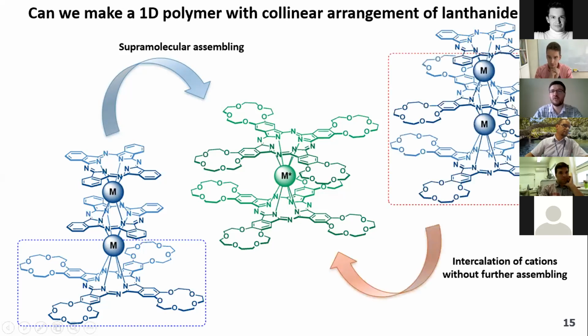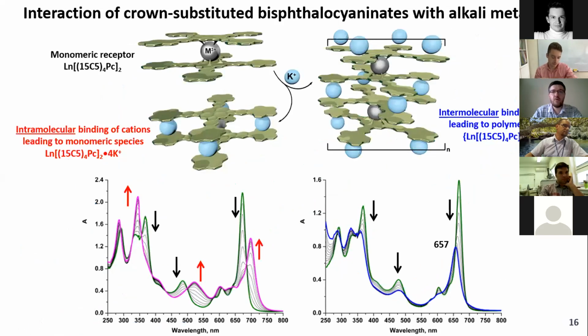But on the other hand, this molecule is also similar to another type of triple-decker complexes with two neighboring crown-substituted ligands, implying that in fact this complex also can undergo similar interaction with metal ions. So ions can intercalate between crown-substituted ligands. In fact, both types of interaction can be observed. Luckily, it is very simple to differentiate between them by spectrophotometric titration. In the case when intercalation of cations occurs between ligands, we observe a bathochromic shift in the UV spectrum. And when formation of supramolecular polymers occurs, we observe hypsochromic shifts according to the exciton model of chromophore interaction.